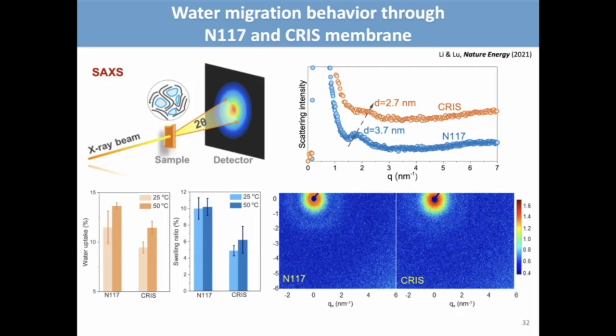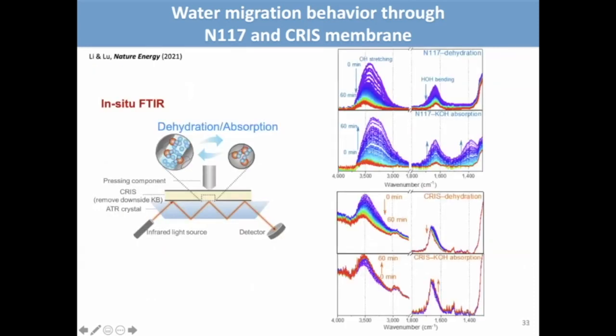So we performed small angle X-ray scattering to measure the water cluster size within the two different membranes. You can see the modified membrane has a much smaller water cluster size compared to that of the commercial membrane, which is consistent with a much lower water uptake of our modified membrane, as well as the much lower swelling ratio of the modified membrane. So that is the key to the restrained water migration, as well as the polysulfide crossover.